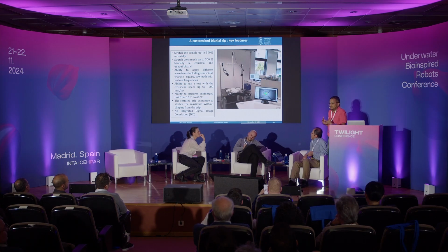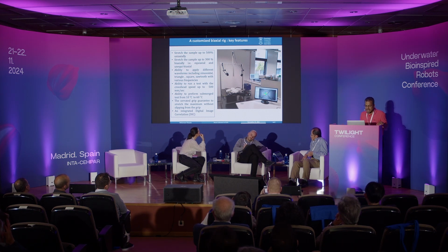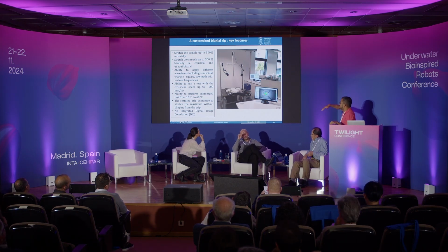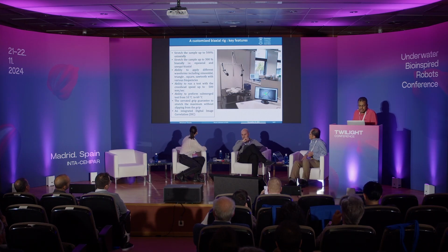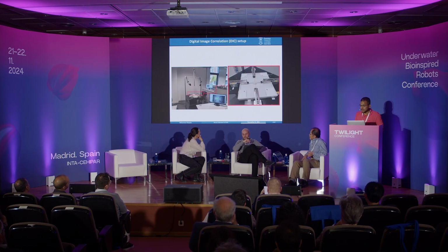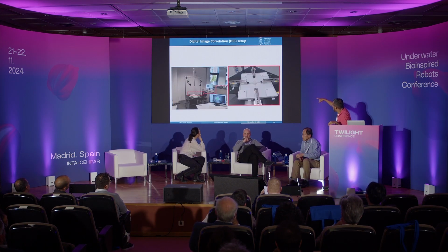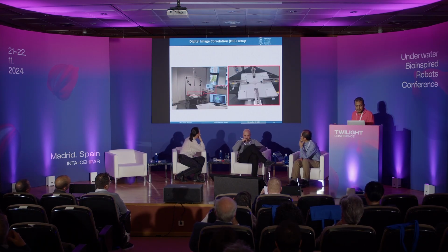And the sensor is very, very sensitive. So we have a 5 or 10 Newton to 2 kilonewton load cell. So it's a large range. And you can test biological tissue or hydrogel and so on. And we have different types of waveforms, so square, triangle, sawtooth, and sinusoidal. So you can use different frequencies and waveforms during your fatigue test. So this is the close look. This is the biaxial sample, the cruciform sample, with the DIC, and you can see underwater.